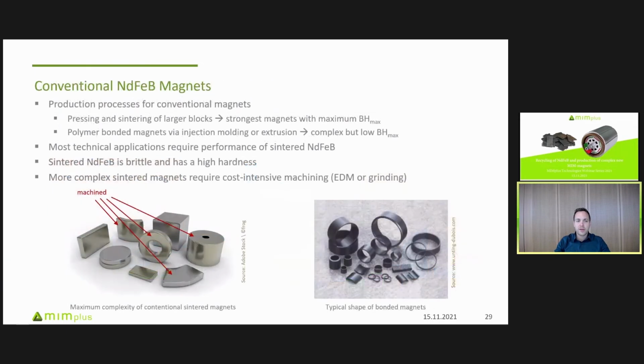Neodymium iron boron magnets are produced in two main state-of-the-art processes. The first is the pressing and sintering of larger blocks, for producing the strongest magnets with the highest energy product available for permanent magnets. But the problem is that conventional pressed and sintered magnets can only be produced as larger blocks, which are not very complex. If you want to produce more complex magnets, you need cost-intensive machining like EDM or grinding to realize magnet shapes like this arc, these rings, or other, let's say, quite simple geometries.